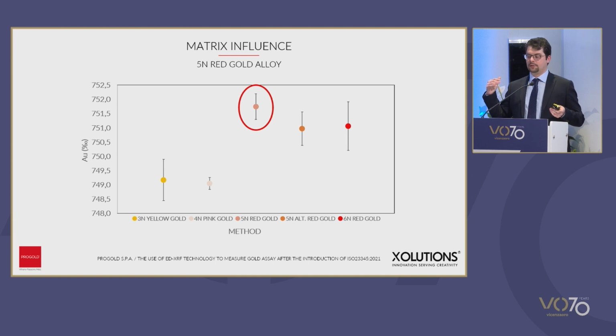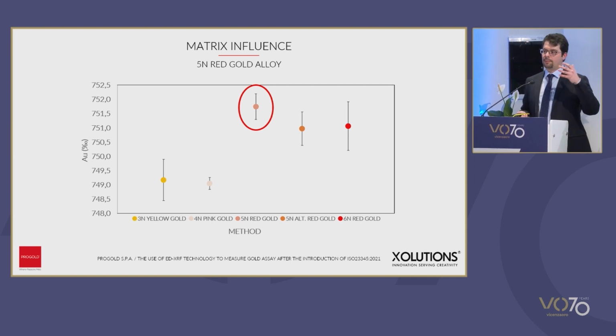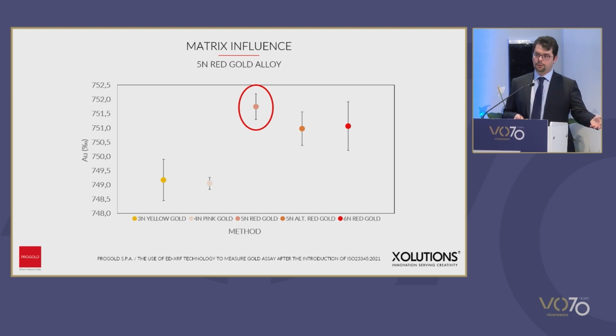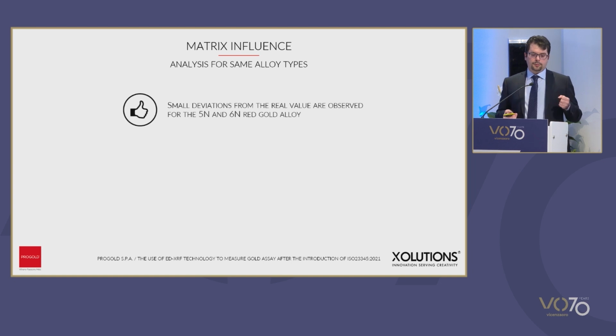where we have a composition which is pretty similar, and with a large quantity of copper, we have good results, although they are not perfectly in line with the results achieved with the specific test. While as we go towards pink or yellow gold, we will find those big differences that we had found in the previous test. So what can we deduce?